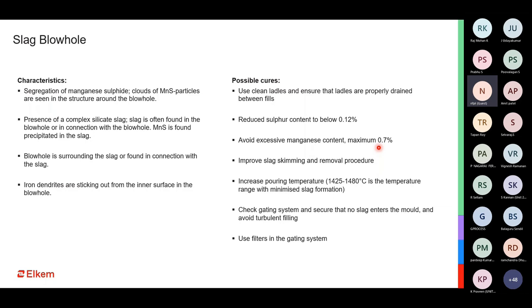So how do we resolve it? We use clean ladles. We make sure that our metal handling systems, metal handling vessels are always clean. We make sure that we have a good control on the manganese and the sulfur in case of gray iron. We make sure that we have a very efficient slag skimming and removal process, and it should happen as late as possible so that you are able to take away any slag which is generated while melting, while additions, and during transfer. Like I said, you need to have a control.